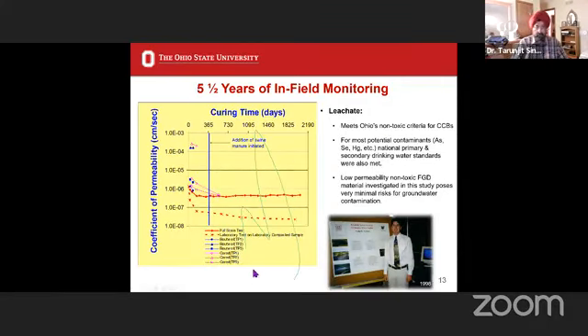But I agree with you that these Boutwell tests, code, or many, many methods are out there. They can work well for materials that are relatively homogeneous. In this case, the FGD material sometimes can have clumps in them, and that can make things even worse. So our recommendation has been that, as generally is done, give ourselves a factor of 10. In the lab, let's get a permeability value of 10^-7, if in the field we want 10^-6.